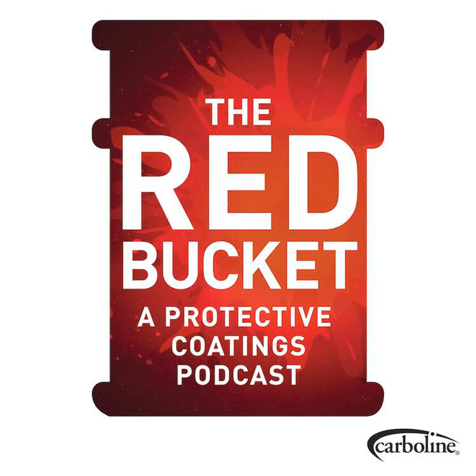And so we took some galvanized panels, some thermal spray metalized panels, and some panels coated with, in this case, a two-coat inorganic system. So we had that zinc-rich silicate type primer, and then we put a silicate finish, so an inorganic finish that allows for breathability. It allows for the moisture and the electrolyte to come through. It allows for continued cure of the silicate resin system so that you get the patina to form, but you also get that increase in adhesion over time.